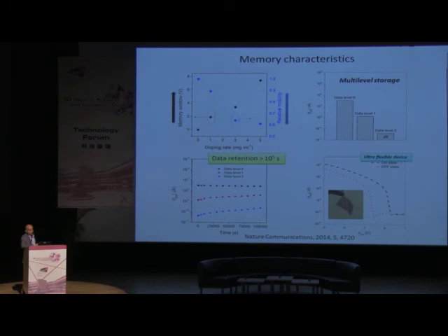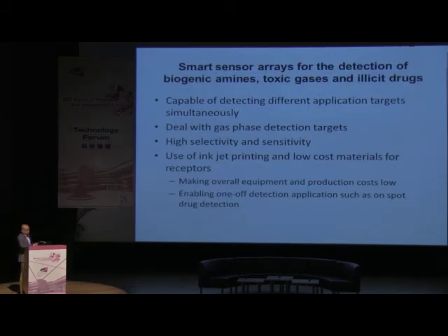And since the memory window is quite large, we end up with multi-level data storage. You can store up to 2 levels, and with light you can go up to, again, 1 more level of data. This is an ultra-flexible device. We just successfully made this with just 10 micrometer thickness, so you can just cut it like paper. And the retention time is not bad, it's good. This is just a proof of concept.